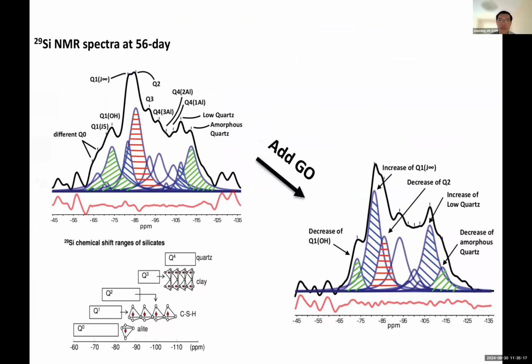So going back to fundamentals, what happened there is if these are silicon nuclear magnetic resonance or NMR spectra at 56 day. And if you look at the one on the left, it is the geopolymer, in other words, activated fly ash without adding any graphene oxide. But once you add graphene oxide, even at 0.02%, the hydration products change significantly. Of course, this is a very busy chart.